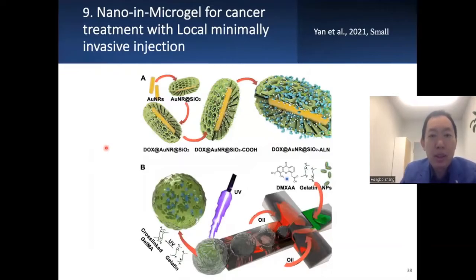And this is another example of tumor treatment. So instead of tail injection with multiple doses, it's also possible to have one dose of treatment with a local, minimally invasive injection. In this case, we first have this gold nanorod, which is photothermal responsive, and then we grow an MSN shell on top of this gold nanorod. In this case, the shell is porous. It can load different kinds of drugs. And we can also modify the surface freely, because this silica oxide is very easy to modify. So you can have some ligand.